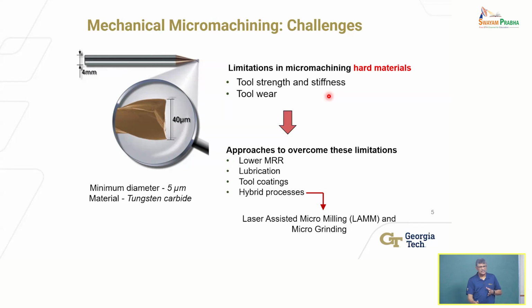So most of these tools tend to be made out of a fine grained tungsten carbide, which is the same material that's used for even conventional scale cutting tools. And they may have coatings and so forth. Although coatings for these tools is not that simple to do. Early days when people were making these tools, if you looked at the tool under a high magnification microscope like a scanning electron microscope, you'd see that the coatings are very, very non-uniform. Clumps of material as opposed to nice, thin, uniform coating. But they have improved. These days you can buy decent quality coated cutting tools, depending on the manufacturer.